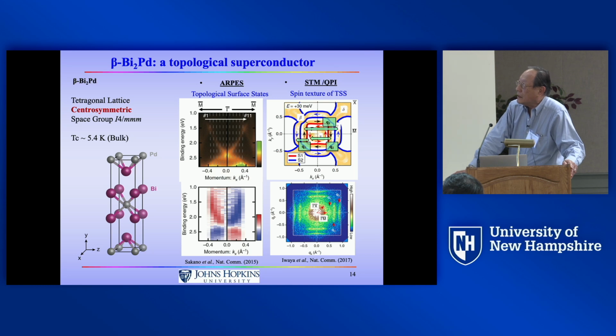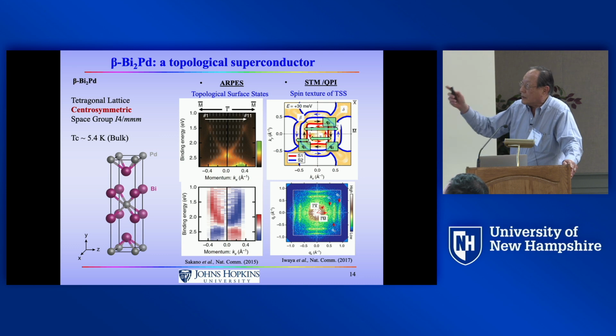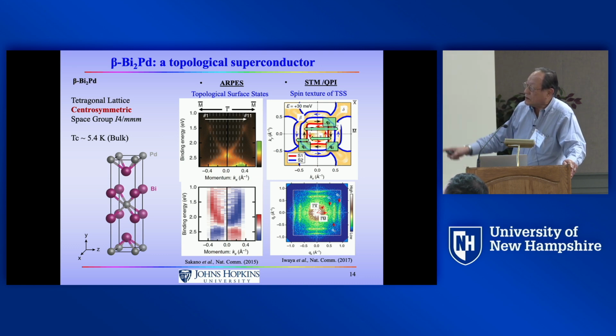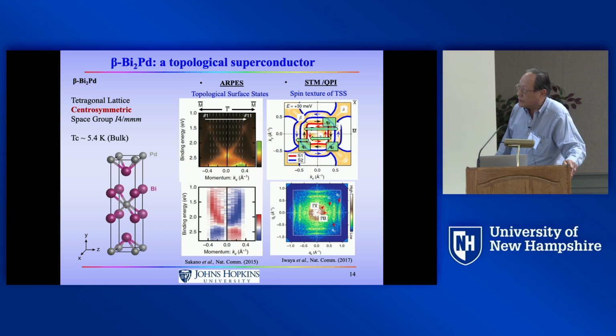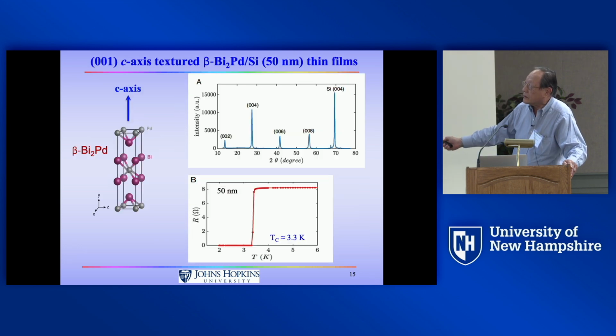Okay? So, which triplets? We tried. Theorists suggest a topological superconductor might be a triplet. So we tried various. I won't tell you the failures, I'll only tell you the success. This is the success: beta bismuth palladium. The ARPES, etc., say it's topological, so we tried to make that material. The material structure is shown there. It's a layered structure.